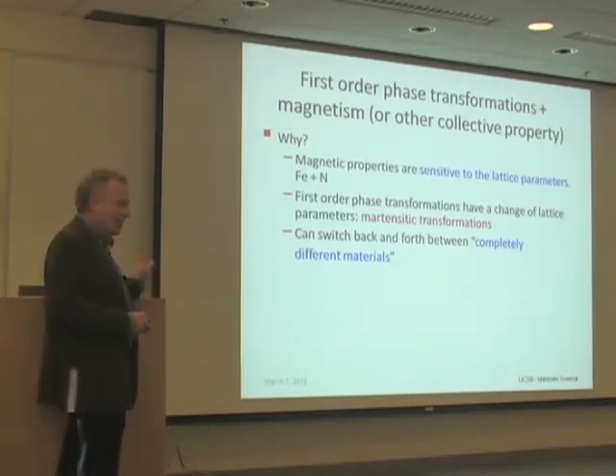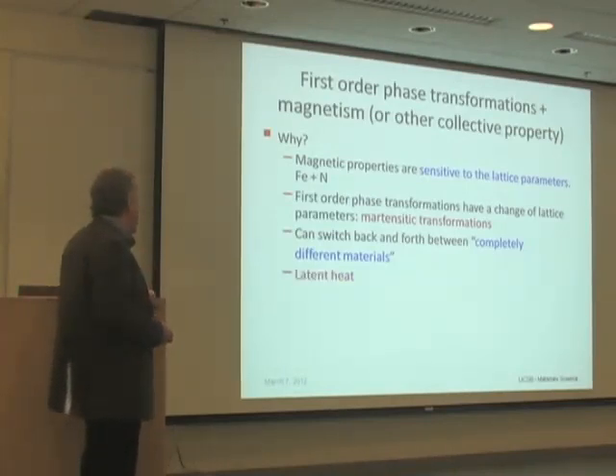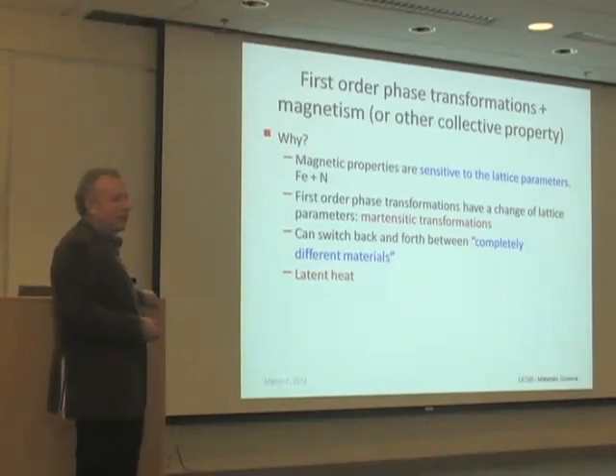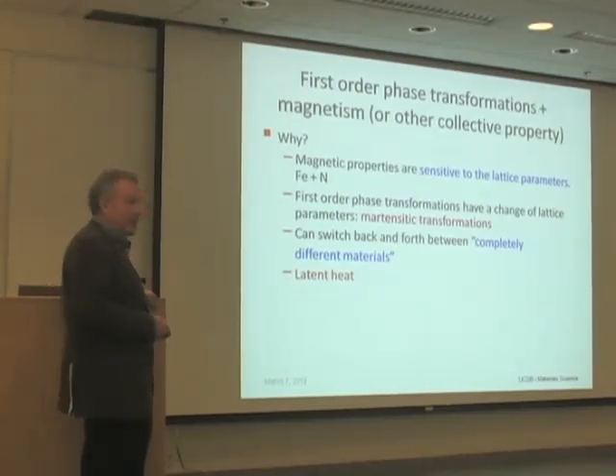That's what I'll try to do. The other thing about them is their phase transformation, so they have latent heat. And so that's critically important because you want to be able to take a large fraction of that latent heat and convert it into electricity.